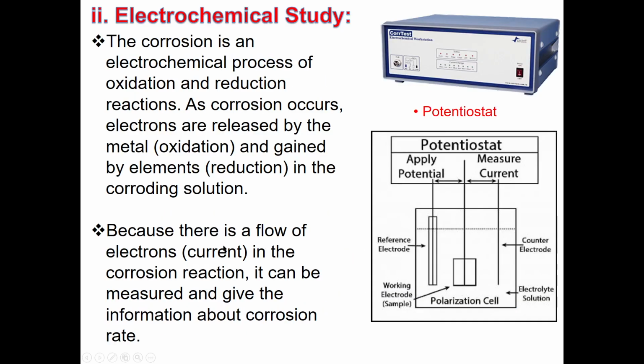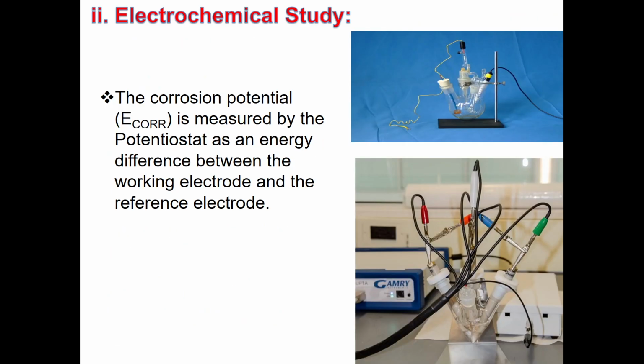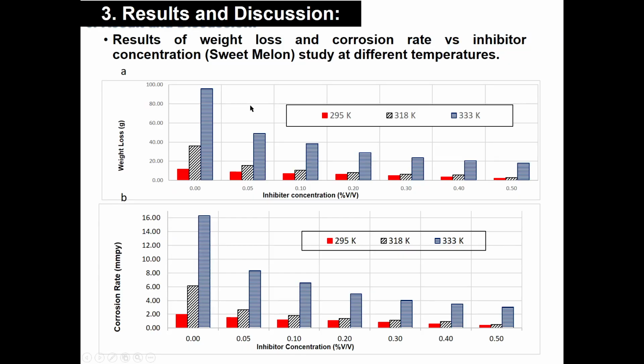And in the electrochemical study, we also did that to confirm the phenomenon and the potential of the corrosion inhibitor. Corrosion, we know, is an electrochemical process of oxidation and reduction. So what will happen during the corrosion? The electrons are released by the metal and then gained by the elements in the corroding solution. So there is a flow of current which we can measure, and from that we can find out the corrosion rate. So we use this method also, the electrochemical study, and we find out the E corr, which we measure from the potentiostat as an energy difference between the working electrode and the reference electrode. We also calculate the Gibbs energy and other parameters.